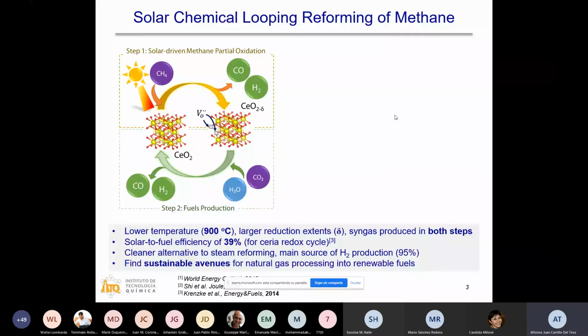So why is this process interesting? First, it allows us to lower the process temperature down to 900 degrees Celsius because we are using methane as a reductive agent. We will also obtain larger reduction extents at these lower temperatures. And syngas is produced in both steps. And this obviously affects the solar-to-fuel efficiency of this process, which by calculations of Professor Jane Davidson's group from the University of Minnesota is up to 39% for the ceria redox couple, which we can compare to traditional thermochemical cycling, with an experimental solar-to-fuel efficiency record of 5.25% obtained by Professor Steinfeld's group at ETH. And also, it's a clean alternative to steam reforming, which is the main source for hydrogen production worldwide. It represents 95% of the hydrogen produced.